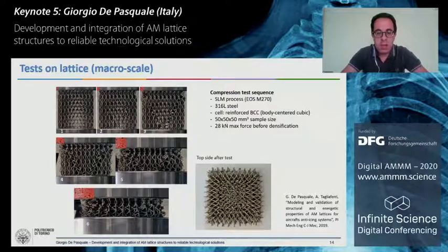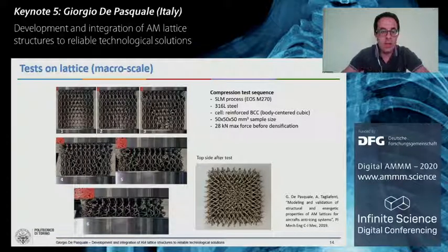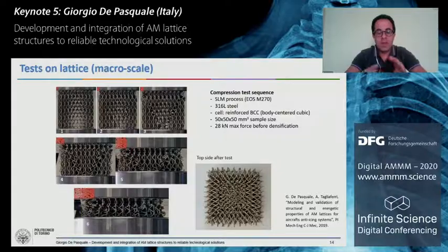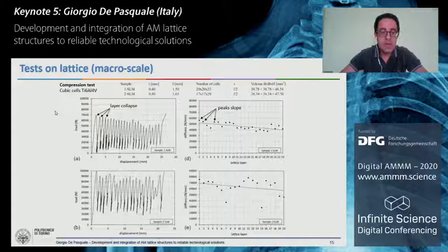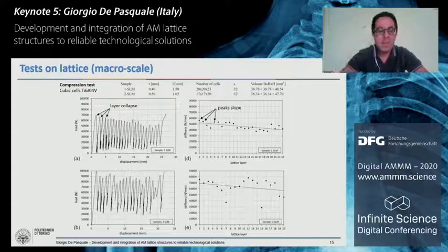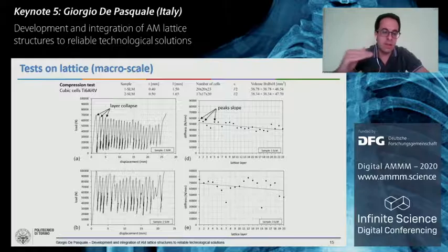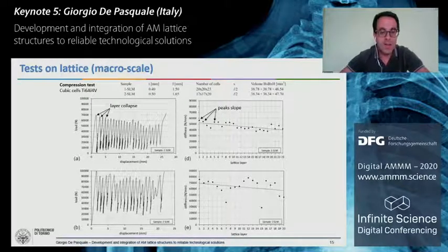Here we have a different shape of cell, but also a different thickness of struts. Just to give an idea about our approach, which is to investigate and cover different cases of dimensions and shapes of the lattice to provide the validation of predictive calculations. In the case of macro scale test results, we have diagrams like this. Each peak corresponds to the collapse of a single layer of our sample, and every peak also reports the thickness and the stiffness, mainly, of each of the residual layers that survived in the samples. So in a load-displacement diagram, we have a behavior like this.